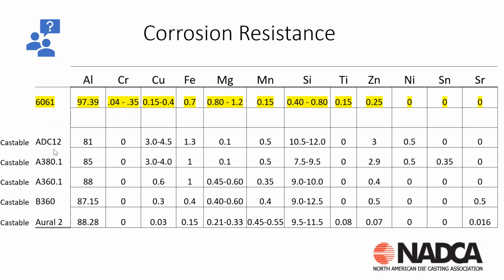Now comparing that to these castable, die-castable alloys, you had mentioned ADC12, how does 6061 compare? Well, we can see that ADC12, 380, A360, B360, and Aural 2, and we can see the copper levels decrease as we go down this chart. So as we move down from ADC12 to 380, very similar copper levels. Then in A360, B360, and then Aural 2, copper levels continue to drop.